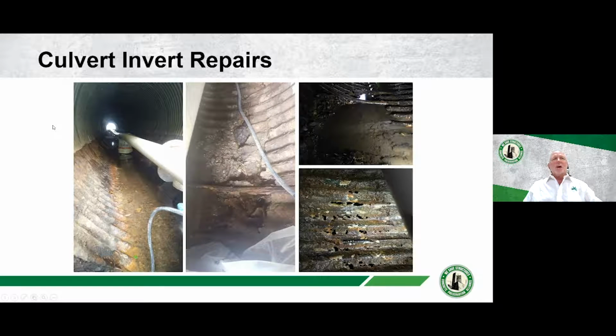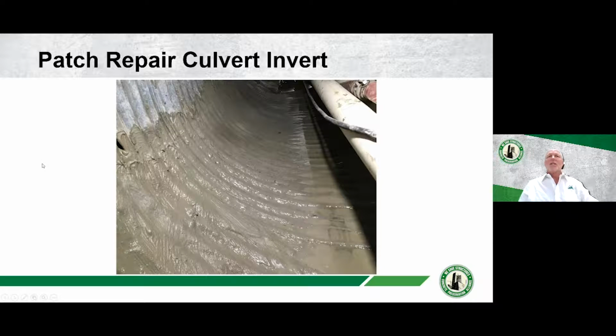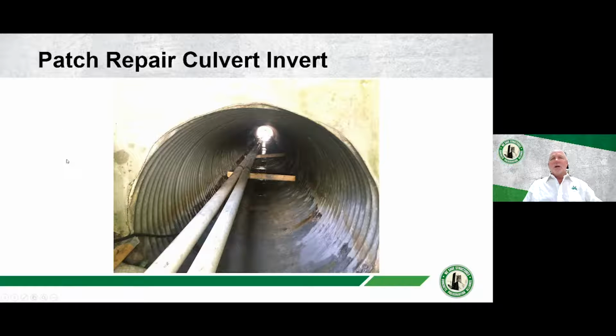Here's a look at the inside of the pipe. Once we got all the junk out of it, you can see here some of the holes in the invert, some of the invert that was missing. So what had to be done here is all that had to be patched up. So the geopolymer material was mixed up in a mortar form and a slurry form, and the whole bottom of the invert was patched ahead of time to seal all that off, to dry it up, and to get a good surface to spray to. Again, here's a look at the setup with the diversion through it, and you can see in the bottom here how the bottom of that culvert has been lined.